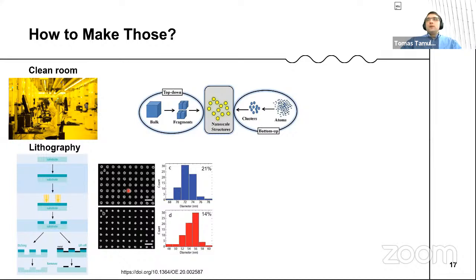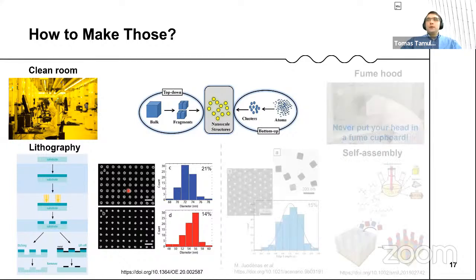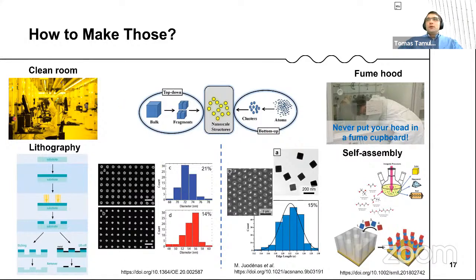So why not to use something that happens by itself, some bottom-up approach? So you need to have a fume hood, not the clean room then. Yeah, don't try to do it like I show you here in the example. And then you have to do some chemistry and synthesize the nanoparticles that you like. And then if you have some template, you can order them. And then it ends up as something that looks really similar. And these are the TEM images of the wet-chemistry synthesized nanoparticles, and their size distribution is like 15% for this particular example here. So it's in between, but it looks much better when you look with the TEM, and it promises some good optical properties as well.